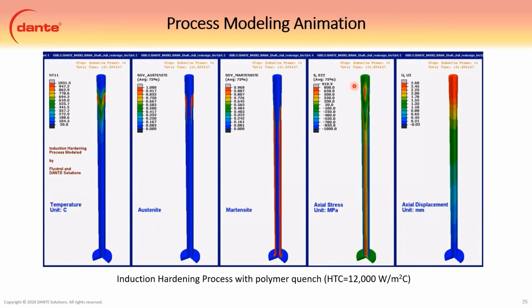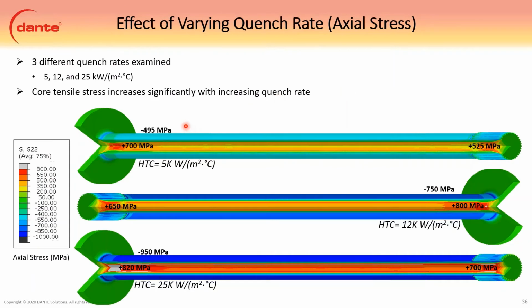But so this is a scanning process. What we ended up doing was looking at the effect of quench rates on the stress. Following intuition, the lower quench rate reduced the stress. You can see up here 5 kilowatts per meter squared C drops us down to about 700 MPa in the core, whereas what they were actually running, 25 kilowatts per meter squared C, gives a tensile spike of about 820 megapascal. Granted, your surface compression is a lot more, but if you can't stop cracking, it doesn't matter what your surface compression is, if you're cracking near the core. So they had to reduce the tension. What ended up occurring was they just reduced the pressure in the spray to reduce the heat transfer coefficient.